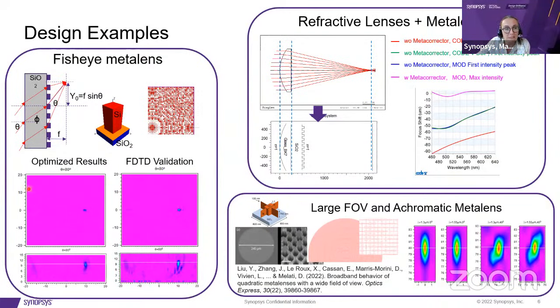What we can see on the right, at the top, is the visualization of the propagation of the beam. The metalens is located at 0 value here. And we can see that for different angles of incidence, the focal point remains at 10 micrometers in that case. We can also have a visualization of the field over the focal plane. And a validation was done using FDTD because it was really important, really mandatory on our side to validate the accuracy of the MetaOptics Designer engine for the propagation aspect.